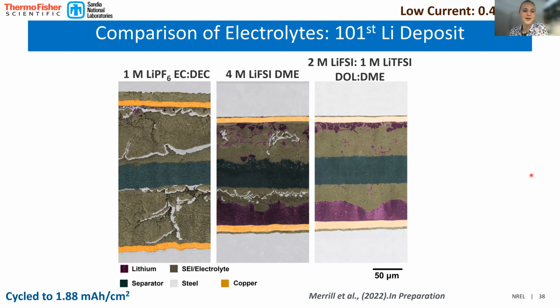Okay, and now comparing this at long extended cycling, so 101st lithium deposit, you can see that in the carbonate electrolyte, all the lithium has been consumed and has been converted into SEI. There's large gas bubbles, large cracks in the SEI, and pretty much everything's mostly disconnected from each other.